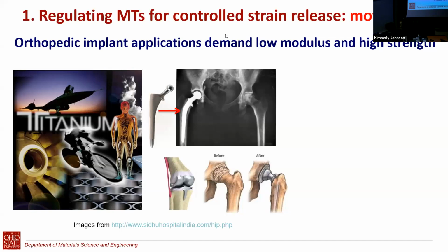If you know the Frank theory about the ideal strength of materials, usually materials yield at 1/100th of the ideal strength or even lower, and the ideal strength is about 1/10 of the shear modulus. So if you want 20 gigapascal modulus and 1 gigapascal strength, you want the materials to yield at 50% of their ideal strength, not 1%. Theoretically, you just can't do it, so we have to use some trick to realize that.